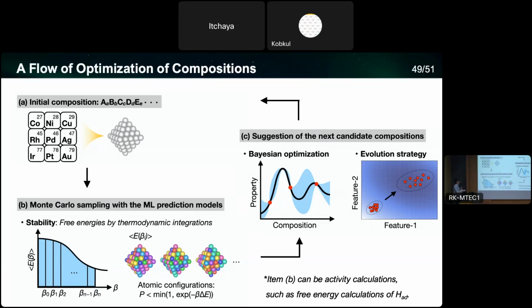And then from the obtained free energy, we give the result to some optimization algorithm, like Bayesian optimization or evolution strategies, to propose what compositions we need to explore in the next step. And then we go back to the composition. We propose it to the composition, and we iterate these cycles until we get saturation. Like in the case of stability, we want to minimize the energy so that the system is stabilized.